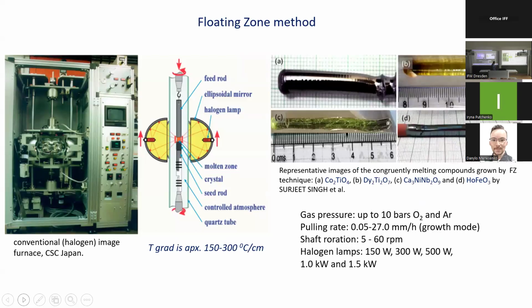Now I talk about the crucible-free floating zone method based on optical heating. As it is crucible-free, that's the main advantage of this technique, so there is no crystal contamination by crucible material. Here you see the general view of a standard image furnace equipped with halogen lamps. This is the control unit, and this is the main body. The most important parts here are the ellipsoidal mirrors, lamps, and there are two shafts, upper and lower. You mount the ceramic feed rod of your material on the upper shaft and the seed on the lower.